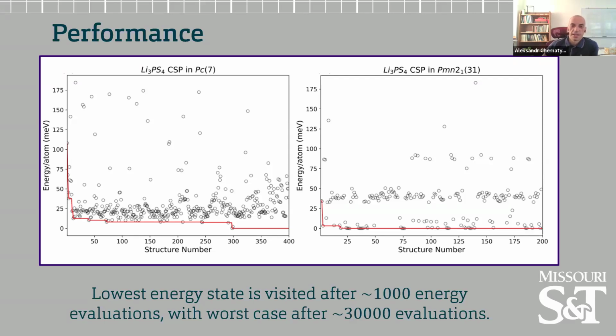The case on the left is kind of one of the worst cases that we have found. In these worst cases, we only found the lowest energy state by the time we hit about 30,000 evaluations. So if you are unlucky, this is how far one would need to go. Again, this is in one particular space group. And so again, this is the question of how certain are we that we have a convergence of our system.